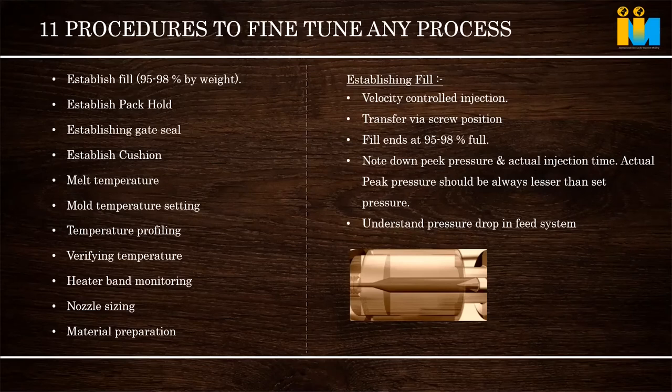And to understand the pressure drop in the feed system, I told you the switchover position is the position from where the material shifts from injection to holding. Suppose in injection I filled the part 95%, and in holding I fill it 100%. Now I stop the holding, so holding will not take place. The screw will go to the injection up to the switchover position, and start refilling and go back. So we get a part which is 95% filled.